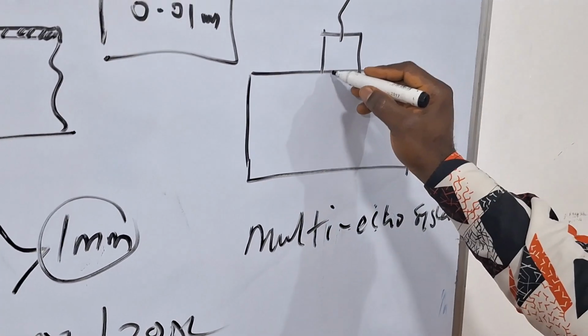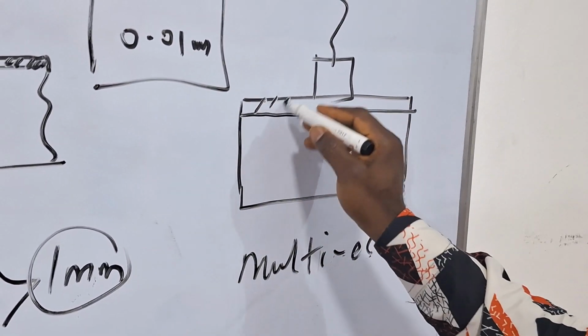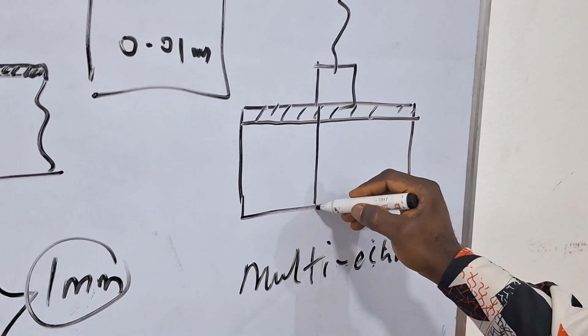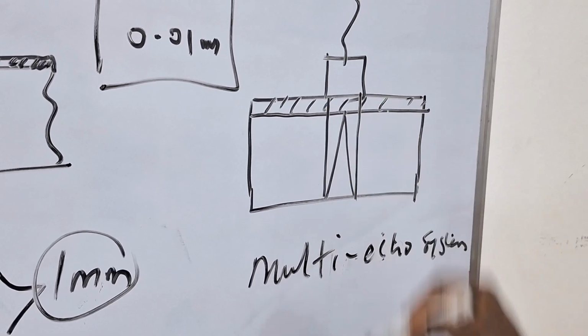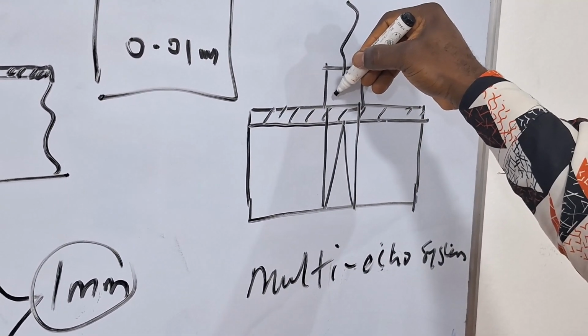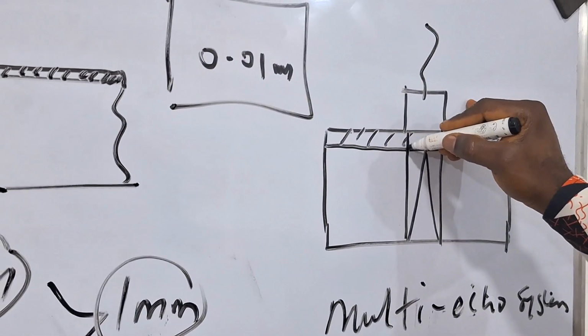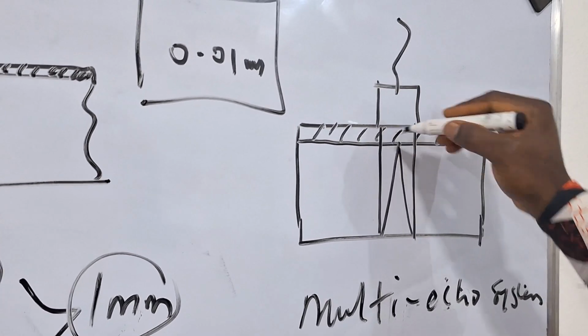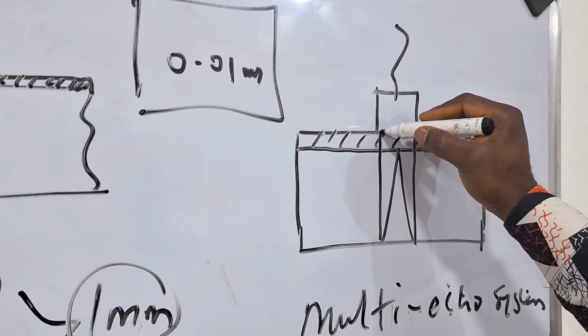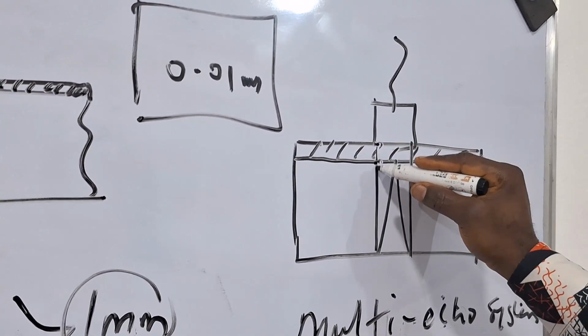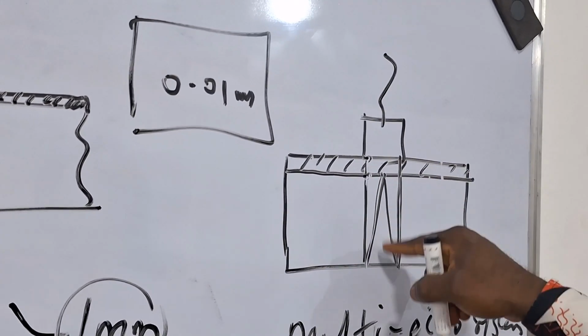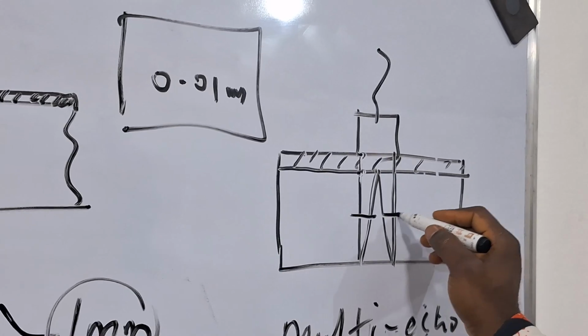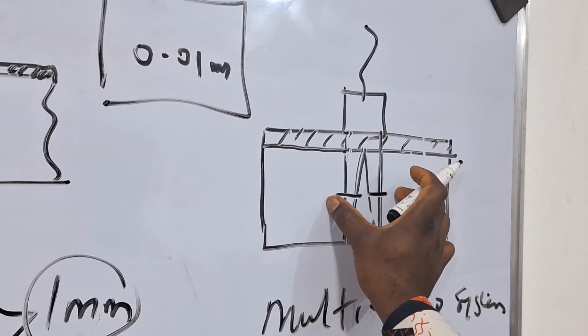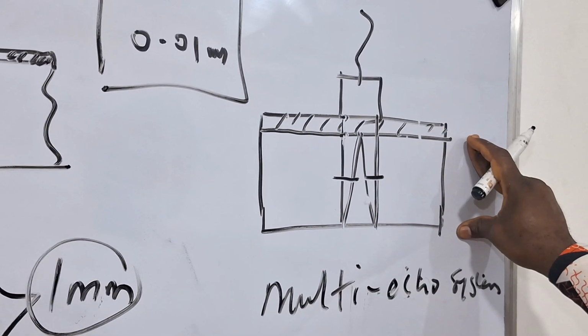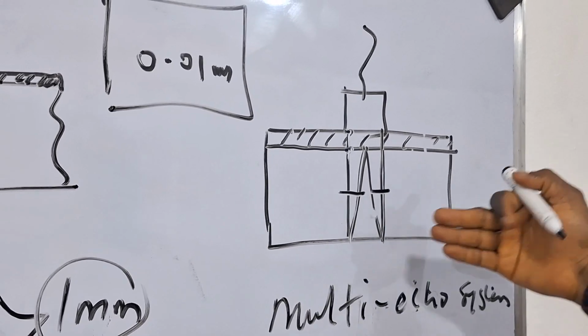What happens is this: the probe, if I have a coating, let's say this is the coating, the probe sends in a signal. Of course, this will be reflected back, reflected back, reflected back. So when this probe sends in the ultrasound, it goes through the coating, it considers the thickness of the coating, and by the time this echo is reflected multiple times, it takes the difference in the reading between multiple echoes. When it gets the same reading, that is what becomes equal to the thickness of the material. It is built into the design of the unit so that it calculates multiple echo. When they are equal, it gives you the final result.